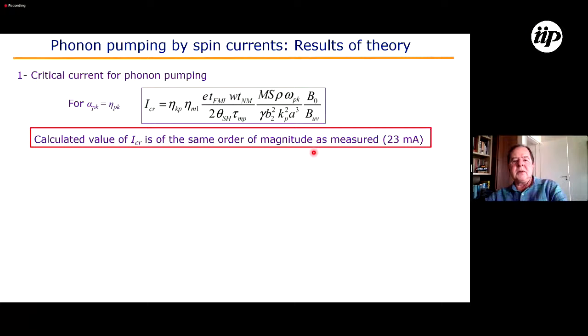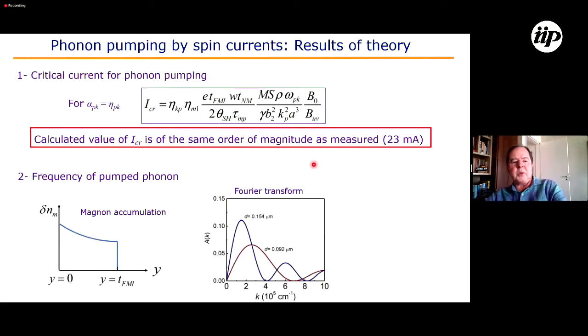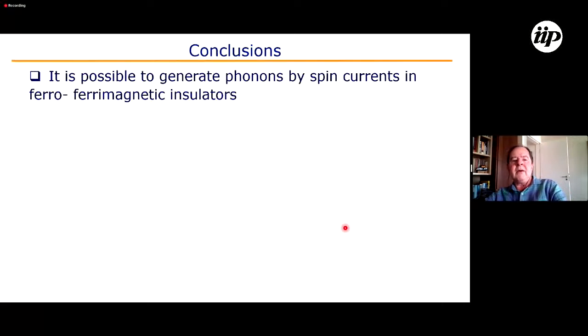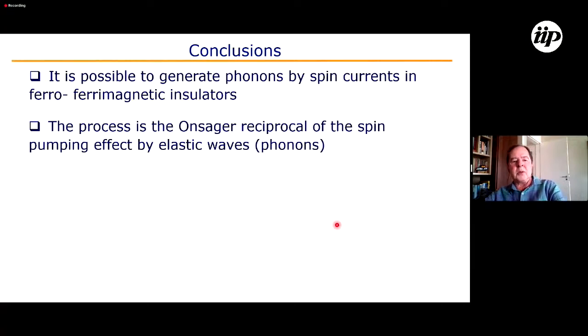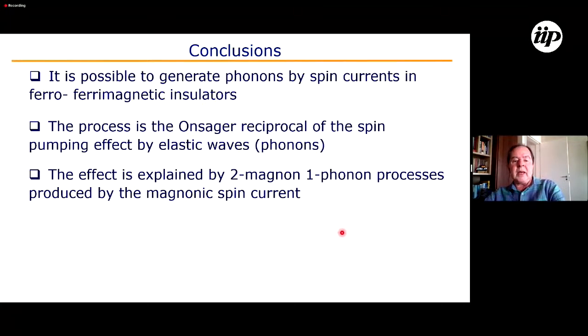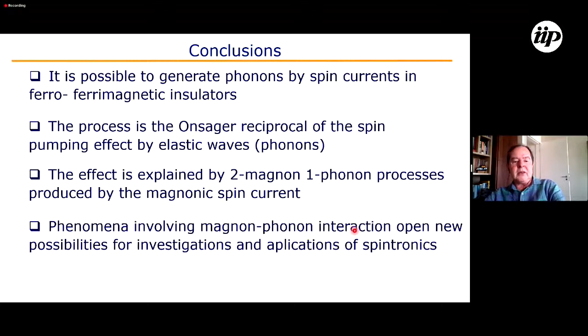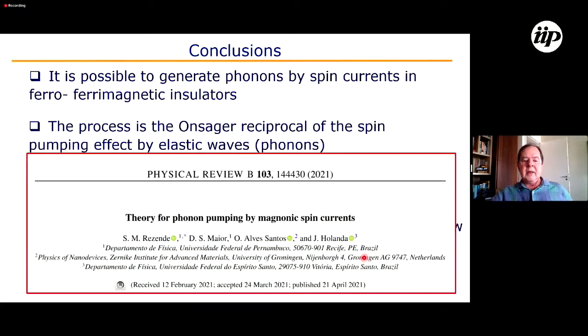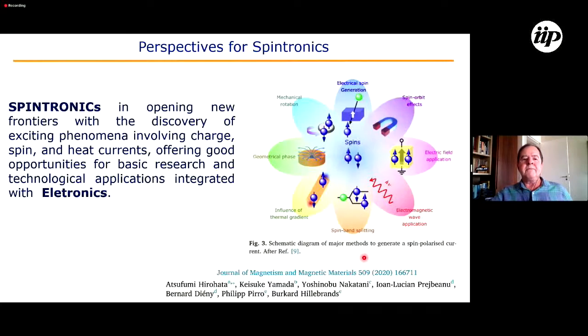We calculated the threshold, and the threshold is in good agreement with experiments. We calculate the Fourier transform, and with this we calculate the frequency, and we have, again, in conclusion, it's possible to generate phonons by spin current in ferromagnetic insulators. This process is the reciprocal of the spin pumping effect. The effect is explained by 2-magnon 1-phonon processes produced by the magnonic spin current, and phenomena involving magnon-phonon interaction open new possibilities for investigation and application of spintronics. The paper with the theory was published in April last year.